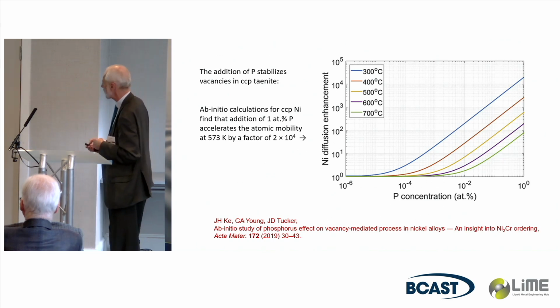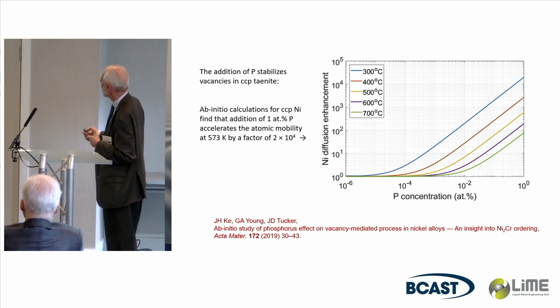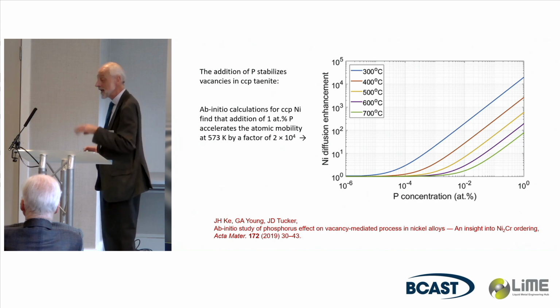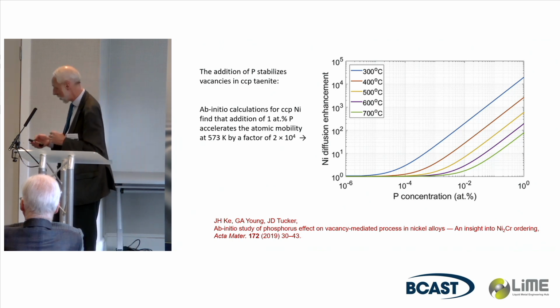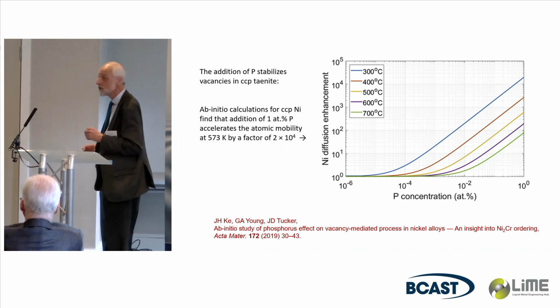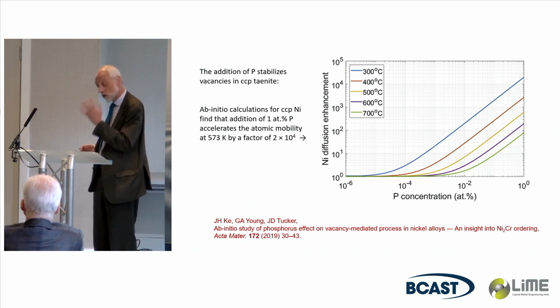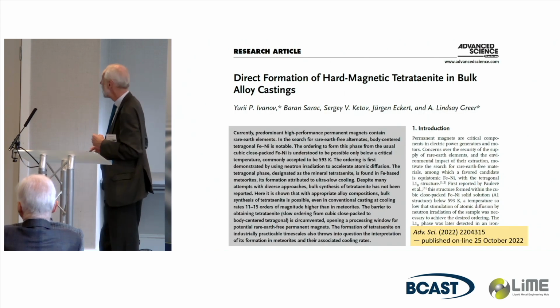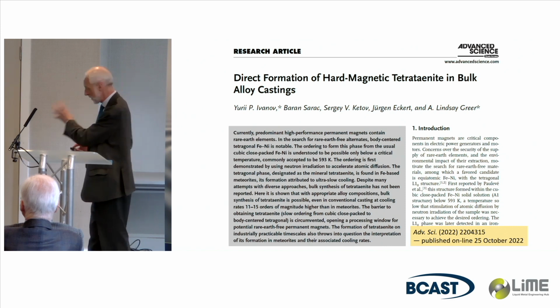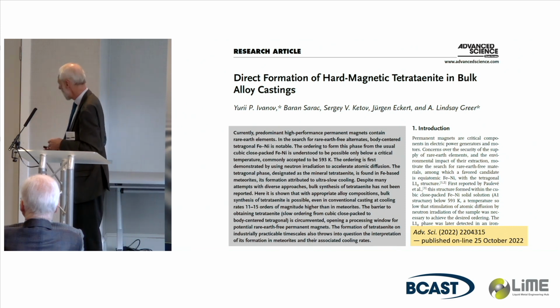Here we're showing, just from the literature and ab initio calculations, that you can get more orders of magnitude enhancement in iron-nickel systems in the presence of phosphorus. So that maybe helps us to see the ordering on a shorter length scale. So this was our paper that came out on this topic in October.